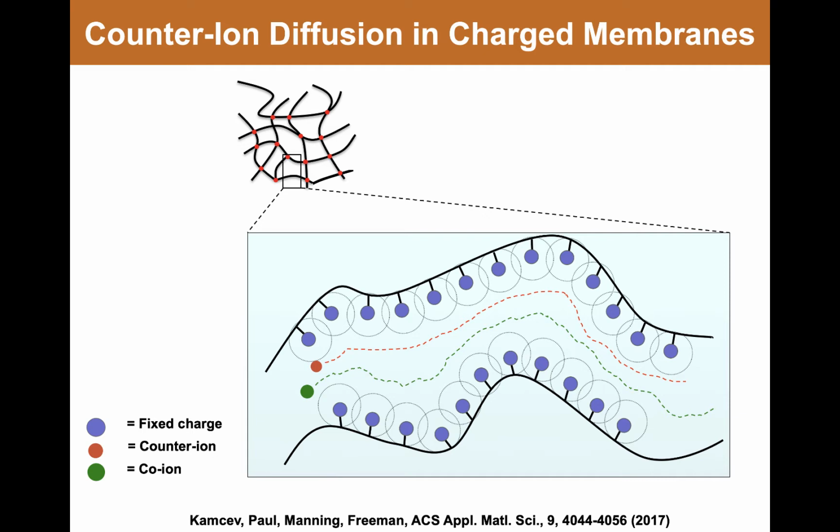We imagine for the free counterions much the similar path. They're staying near their co-ion and staying away from the polymer chains and diffusing, following much the same pathway and mechanics as the co-ions do. And so for the free counterions, or the uncondensed counterions, we're going to use exactly the same model that we use for the co-ions and that I just showed you a moment ago.